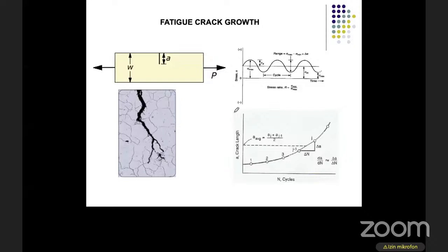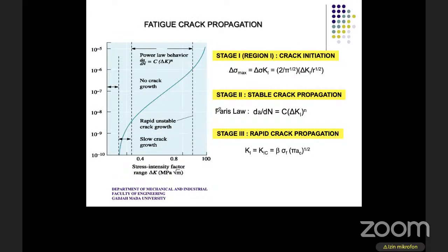And I think this is an example of an experiment to study how the crack grows under dynamic loads. And this is the main focus of our research. And normally, the fatigue crack growth rate behavior of a material can be studied using this da/dN as a function of the stress intensity factor range, delta K. And from this diagram, we can see three different regions, which are crack initiation here, and then stable crack growth, which follows Paris law, and then the final fracture here in stage 3.